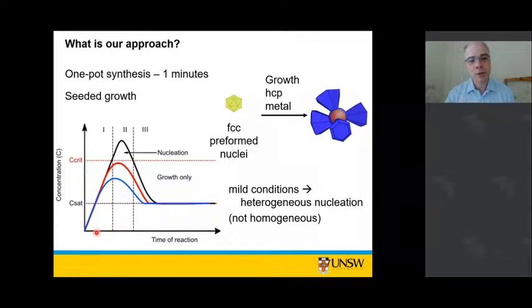So the important thing is that you always want to have a low concentration of these ruthenium zero valent atoms. So if you have your gold seeds in the solution, and then you have a low concentration of these zero valent ruthenium atoms, the only choice they have as they're moving around in solution is to stick onto the gold. You can then form your core shell structures and start to grow your arms.